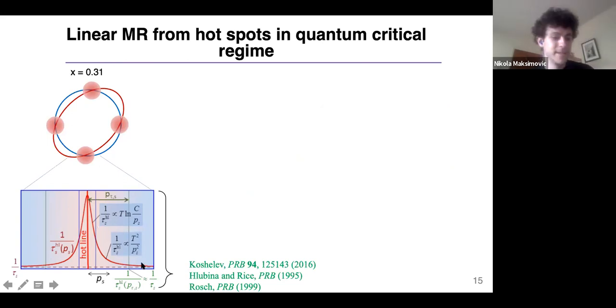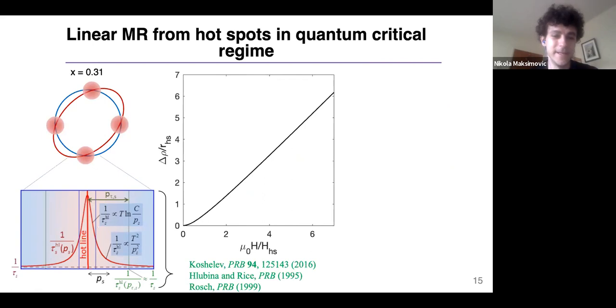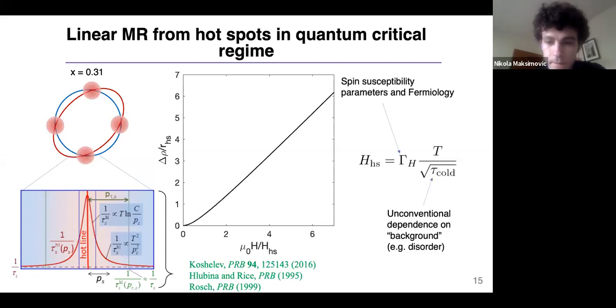And the magnetoresistance that you get from this looks almost identical to the magnetoresistance you get in the previous model. It's basically B squared at low fields and crosses over to linear at high fields. Now there's a few experimental tests we can do.